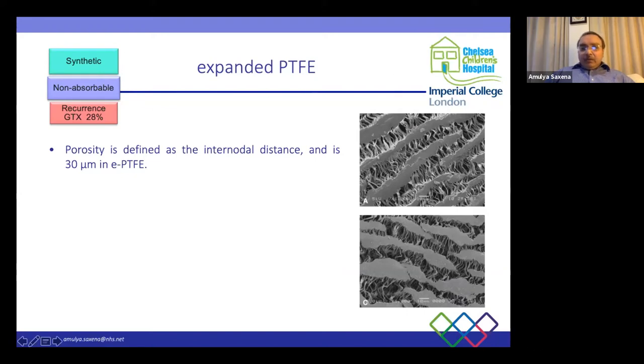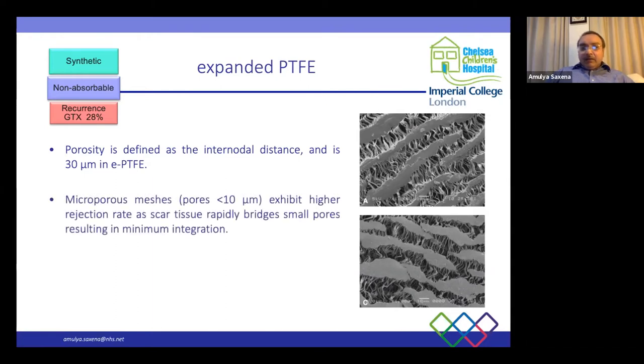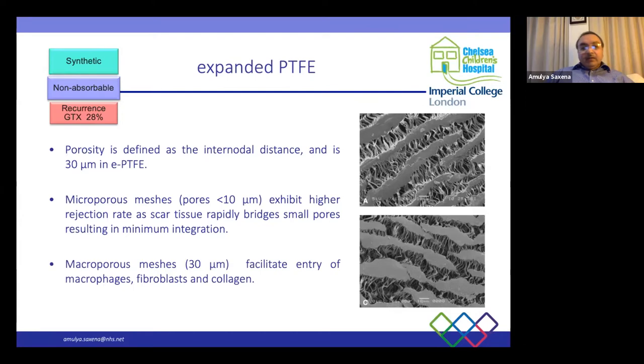Now, what is very important in Gore-Tex is the porosity, that is the distance between the two layers of the Gore-Tex. This is defined as the internodal distance and is around 30 micrometers in expanded PTFE or Gore-Tex. Now, why is that important? As you can see, micropore meshes of less than 10 micrometers exhibit a higher rejection rate because the scar tissue rapidly bridges these holes, which you can see on the side over here, and this results in minimum integration. So you do not use a microporous mesh; you use something like the present Gore-Tex with 30 micrometers, which allows integration of tissues and no blockage by scars. So 30 micrometers is very important. It facilitates macrophage, fibroblast, and collagen entry and integration of this material.